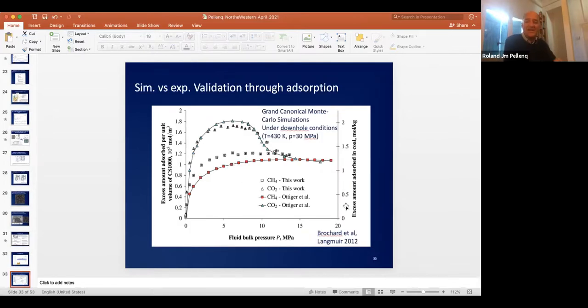All right, what can we do with that? Once we have the simulation of that, we can try to simulate the adsorption of gases into this thing. This is another simulation technique, still Monte Carlo, called grand canonical. So we fix the chemical potential, so the vapor pressure of whatever, methane, CO2 in this case, water could be, and see how much water, or CH4 or CO2, will get into the pores for that pressure on the outside. And then we can plot the amount of molecules in the pore as a function of this outside pressure.